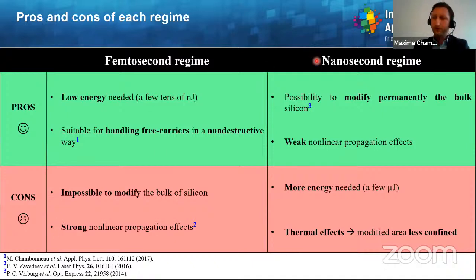But then if you go to the nanosecond regime, so 1 billionth of a second, then it has been shown that it is possible to modify permanently the bulk of silicon. This is due to the fact that when you increase the pulse duration, you decrease the intensity, and thus you decrease the nonlinearities inside the material. However, of course, more energy will be needed, and the main drawback is that, as I said in the introduction, you cannot separate the causes and the consequences, and thermal effects will occur during the pulse, which will lead to a high heat-affected zone.